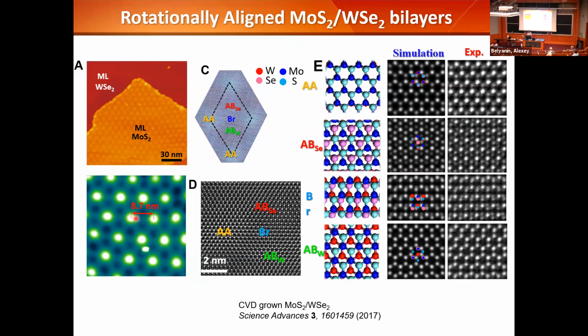Because the supercell, the unit cell, is very small, on the order of 10 nanometers. As you know, when we do optics, we focus light on the material. We typically cannot get better than a few hundred nanometers. And so this is a challenge for us to understand how the supercell with a 10 nanometer spacing controls optical properties.